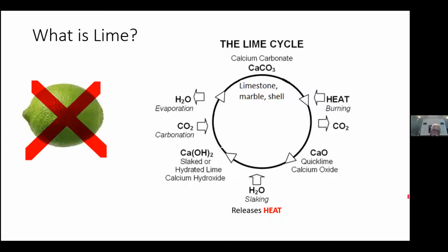So the lime I'm talking about is not the green kind here. Instead, it's the material lime, calcium oxide or calcium hydroxide. And this is a material that starts off as calcium carbonate. That's the mineral calcite. And you find that in limestones, in marbles, and also in shell materials. And to make lime out of calcium carbonate, out of calcite, what you do is you heat it. You burn it, as it's called, and you heat it up.